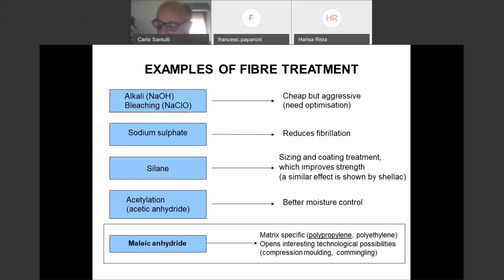What else can we do as well? We can, for example, use acetic acid by acetylation, which can have the same effect, although much diluted, or citric acid, so acid from lemon, and we can get better moisture control, and they become also harder. They tend to become even a little bit more resistant to temperature, because there is another effect which we need to consider, that plant fibers don't get to the same temperature we were accustomed to with glass fiber. Not talking even about carbon fiber, which is way higher. If you remember the thermogravimetric tests, plant fibers degrade at around 300 degrees.